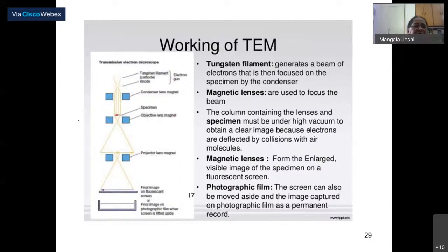If you look at the working of the TEM again, you have a tungsten filament right on the top which generates the beam of electrons, which is focused on the specimen by magnetic lenses as condensers, and the column containing the lenses and specimen. Now this is very, very important for SEM as well as TEM. The column containing the lenses and the specimen must be under high vacuum. If you do not have high vacuum, then the electrons will get disturbed here and there and they will not be able to focus. Magnetic lenses form the enlarged visible image of the specimen on the fluorescent screen,